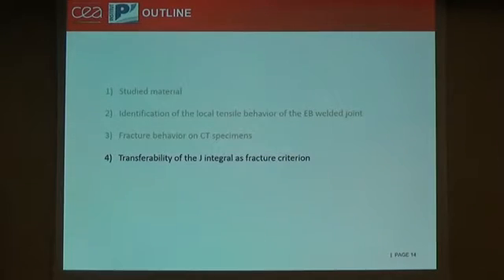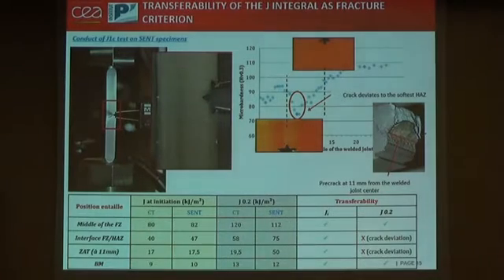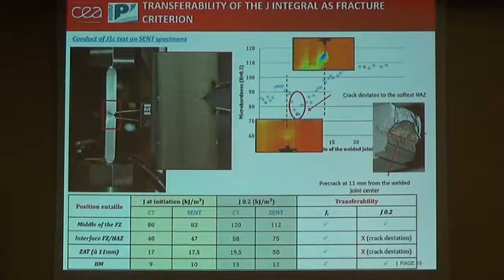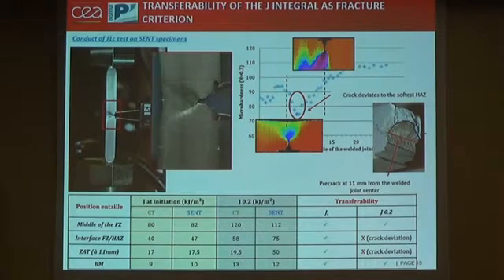The last step is to study the transferability of this J integral criterion to other geometries. Here we propose to use the single-edge notch tension specimen, which better represents real load components. Different tests were conducted with a notch in the base metal and in the fusion zone. The crack remained in the symmetric plane.